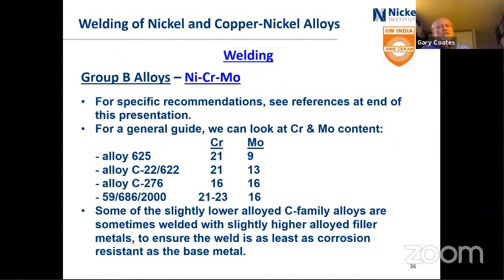But so let's say you have a C22 base material, you can weld it with the matching one, the C22 or 622, or you can go to a 59, 686, 2000 type filler metal because you know that the molybdenum content is higher and the chromium content may or may not be higher, but it's more corrosion resistant. So typically on the C family alloys, you weld it with a slightly higher alloyed filler metal to ensure that the weld is as corrosion resistant as the base metal there.